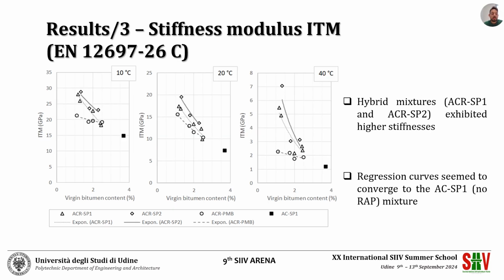Mechanical properties were assessed by means of indirect tensile modulus and indirect tensile strength tests. Stiffness moduli were evaluated at 10, 20 and 40 degrees, showing decreasing values with increasing binder dosage for all mixtures. In addition, ACR-SP2 exhibited the highest stiffness, followed by ACR-SP1 and ACR-PMB. The differences were more pronounced at 40 degrees. This result can be attributed to the highest polymer content present in hybrid blends compared to the wet blends.